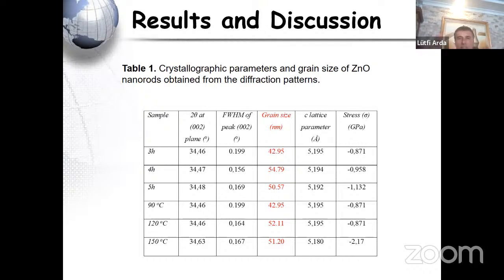Look at here. These are the crystallographic parameters and grain size of zinc oxide nanorods obtained from the diffraction pattern. The first column is the sample, the nanorod, with growth times of 3 hours, 4 hours, 5 hours, and growth temperatures of 90 degrees Celsius, 120 degrees Celsius, and 150 degrees Celsius. The second column is the 002 peak center, and the third column is the full width at half maximum. We calculated grain size, also the C lattice parameter, and the stress for each nanorod.